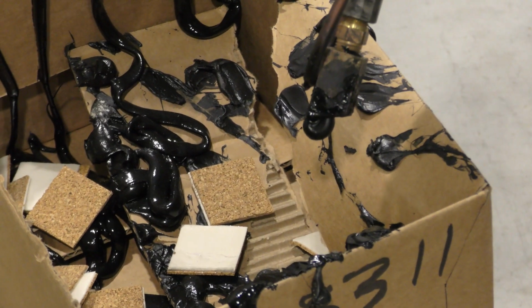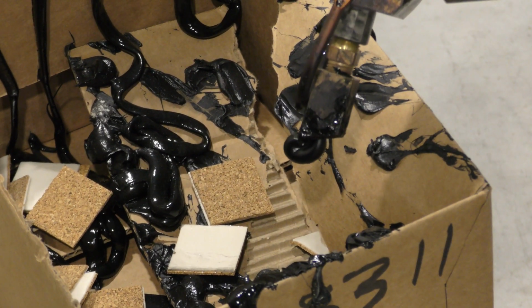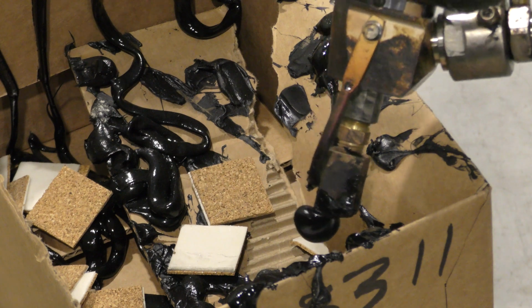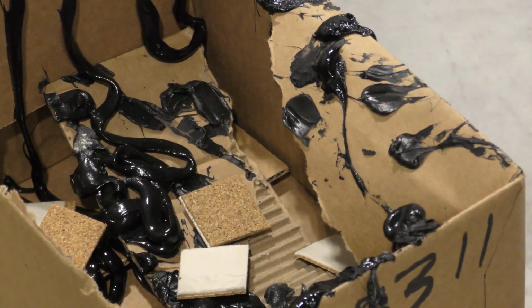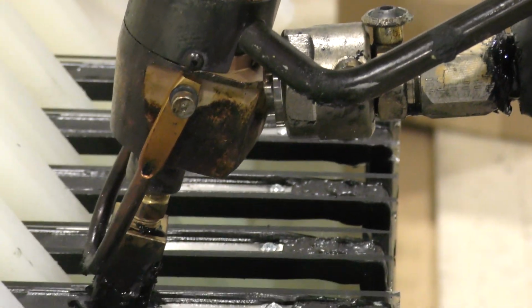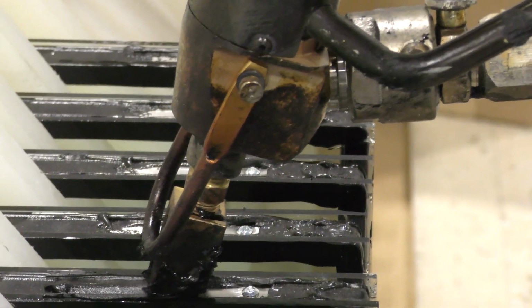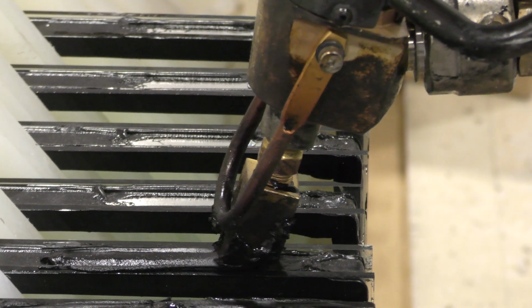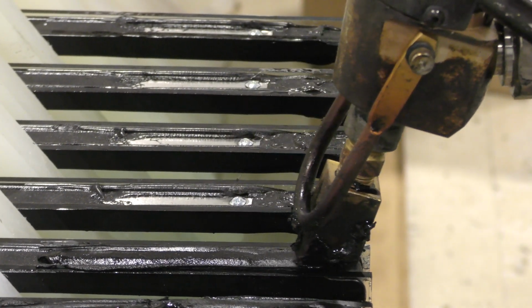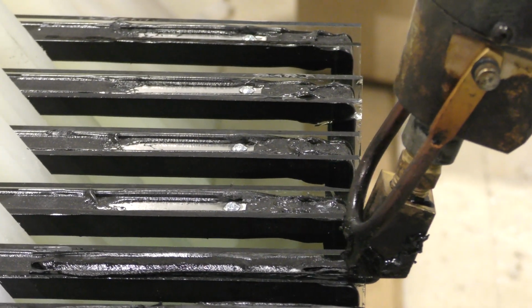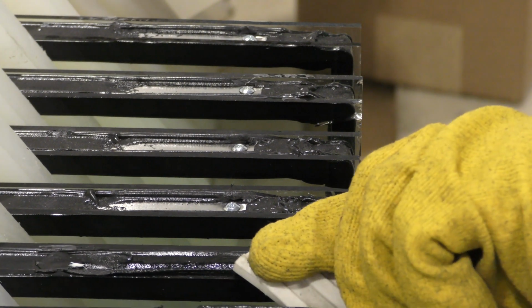Before applying patch sealant to an IG unit, it may be necessary to squirt a small amount, approximately 2 ounces, of sealant from the gun into a waste container in order to move the hot material from the heated portion of the gun to the application tip. If applying patch sealant and smoothing it afterwards, be sure to patch no more than 4 to 5 units at a time. The sealant temperature will become too cold if the IG units are processed in large batches.